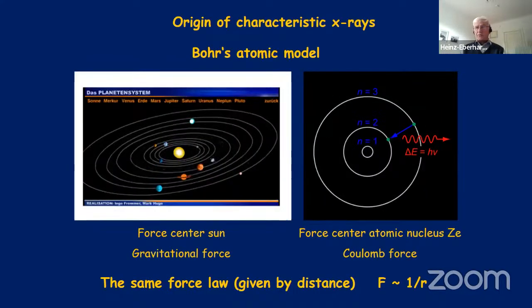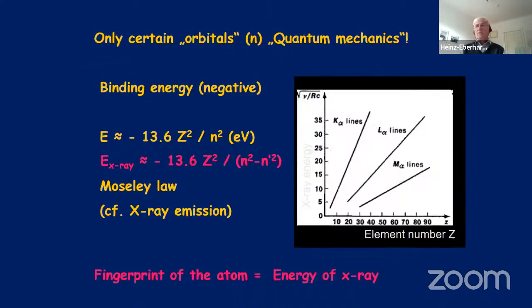So it all goes back to the atomic model, of course, where the binding energies of the levels increase with the elemental number squared. And that gives us a nice feature: here is a plot of the square root of the energy, or the square root of the frequency, over the elemental number, where you just get straight lines for the K lines, the L lines, or the M lines. And that means by measuring the energy, you get a fingerprint of the atom.